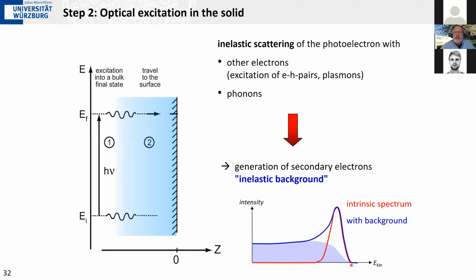And that's shown here. Take, for example, this red spectrum here. This would be, for example, a core level spectrum. If we didn't have these inelastic processes, if we are still with this step 1 here, we have an excitation into this final state energy. And now the electrons start propagating from the site of the excitation towards the surface. Some of them lose some energy and will appear here at lower energies, and then they give rise to this inelastic background. And that's what you often see, that behind such a line or behind a spectrum, you have an increase of intensity, which is relatively structureless,